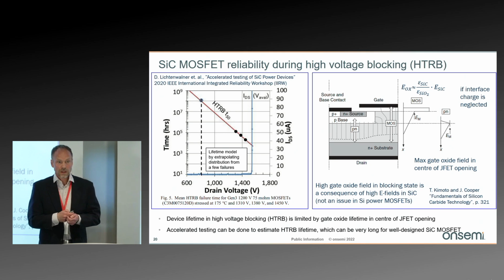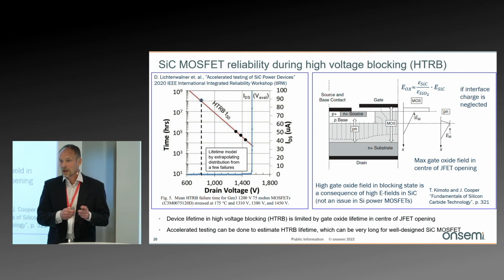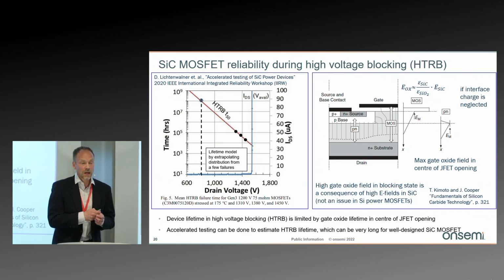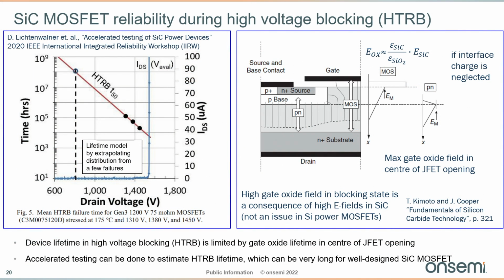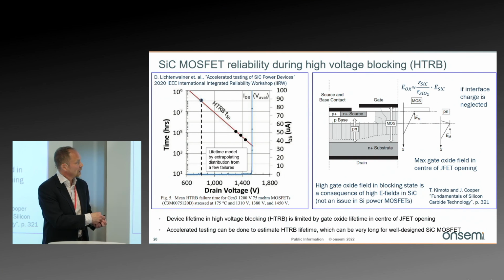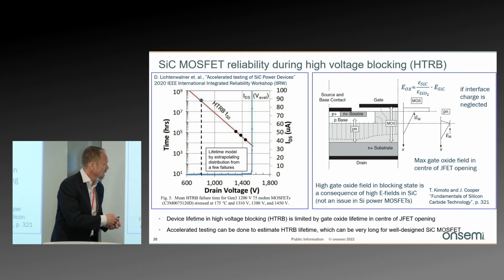And then we have, as mentioned before, also the reliability at high voltage. This is some nice work by Lichtenwalner at Cree, putting a high bias on the devices, measuring until failure due to gate oxide breakdown in the JFET region. Here is a picture from Kimoto explaining the reason for this. In silicon carbide, we have a high field, 10 times higher than silicon. And then we get also a higher field in the gate oxide in the JFET region due to this ratio of dielectric constants.